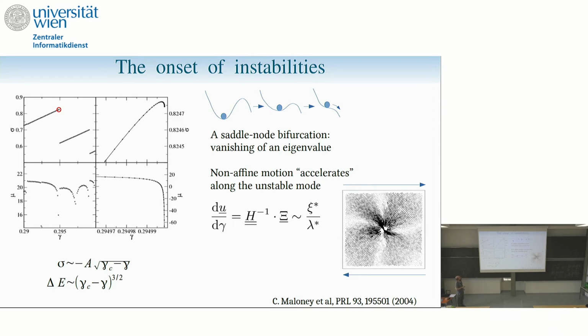So because you have this eigenvalue which is 0, I just said before, this non-affine response is written here. It's the inverse Hessian on psi. Is a missing minus sign? Yes, okay. So the non-affine response is minus H inverse psi. And if you have a mode that vanishes, when you invert the Hessian on something, you have a sum of the inverse of eigenvalues times some coupling coefficients. And so it means that the non-affine field becomes very focused on the unstable mode. So what happens is that the non-affinity will concentrate on the unstable mode. And this is typically one of the non-affine modes, and I'll come back to the physical interpretation of that later. But that's typical, and so what you see is that this mode is highly localized.